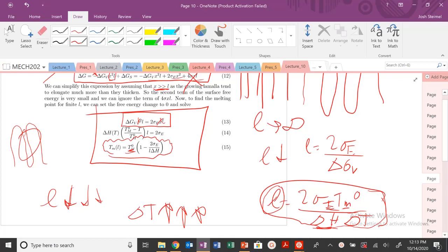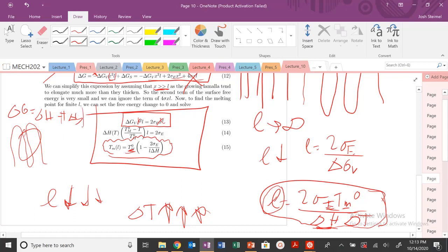So what this is saying is if my delta T increases, my temperature is low. We know from our Gibbs expression here, G equals H minus T delta S, if my temperature is low, this magnitude becomes much, much smaller, so it's not as important. So I could form a lamella, because this is the competition. I need these non-specific interactions between my chains in order to form a nucleus. If my temperature is really low, my conformational entropy term is getting smaller and smaller, so I'm going to need a smaller and smaller thickness, i.e. fewer of these favorable enthalpic non-specific interactions like H bonds or van der Waals, in order to nucleate my lamella structure.